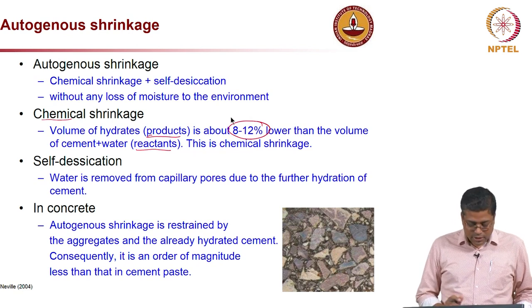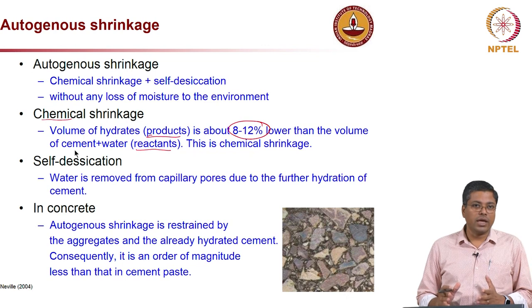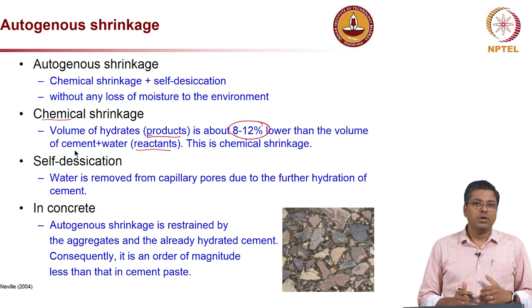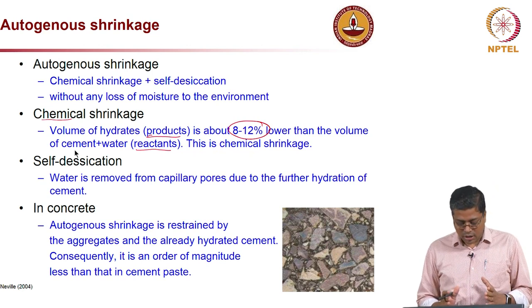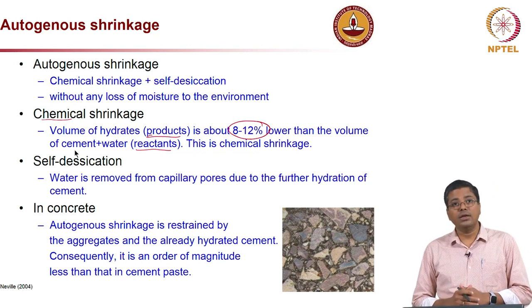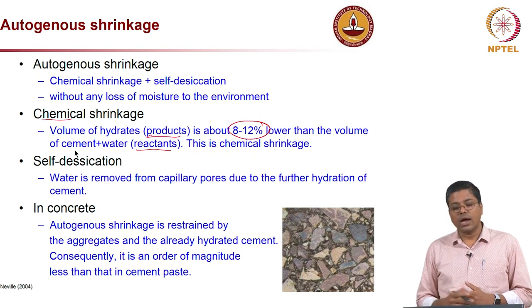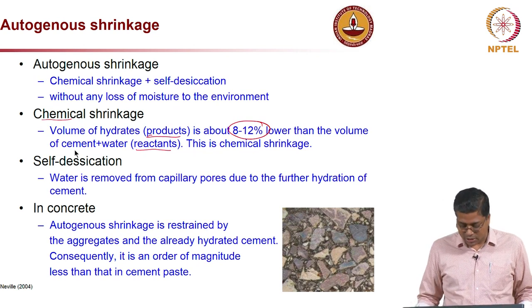So, essentially the cement and water, which are the reactants, have a combined volume which is larger than the volume of the hydrates. In other words, the cement hydration reaction leads to a reduction in volume by about 8 to 12%, let us say 10% volume reduction.